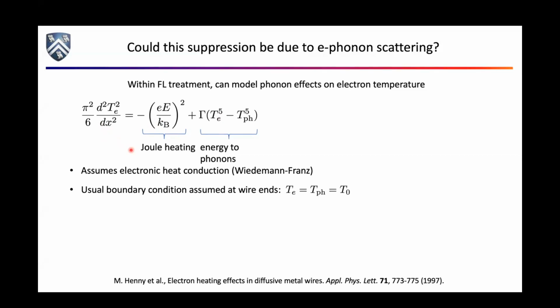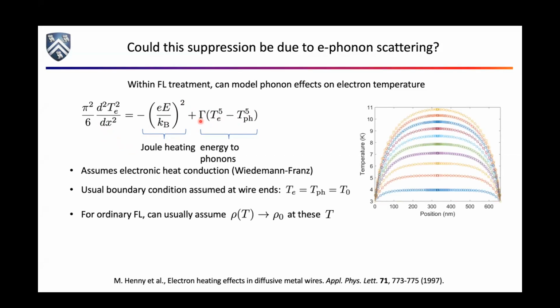If you basically take a very long wire where you know that phonons are going to be important, you can do a series of measurements and try and back out what gamma, this electron-phonon energy loss coefficient, is for your material, right? So what's going on is if gamma is 0, the electrons talk to each other and they trade energy, and there's an effectively heated electronic distribution in the middle. And this is the kind of thing that gives you the √3/4 Fano factor. And if you crank up the phonons, you can squish down the electronic distribution in the middle.